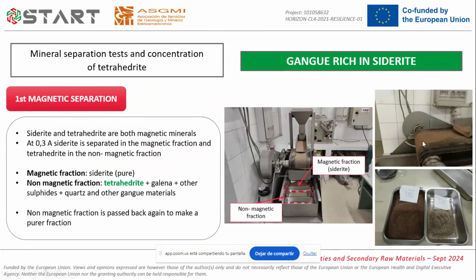It is recommended, as we can see here in the photograph, to leave a thin layer of material so that all the grains can be attracted by contact to the magnet, which is placed here. So what we have after this procedure is a magnetic fraction, which is really pure siderite, and the non-magnetic fraction, which is the tetrahedrite together with galena and other sulfides, plus quartz and other gangue material. The non-magnetic fraction is passed back again in order to make a purer fraction. In our case, we repeated this process 3 times.